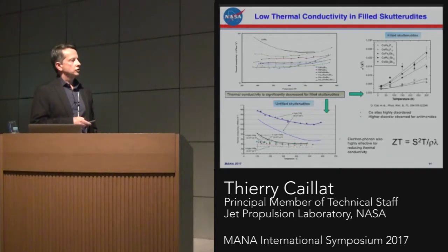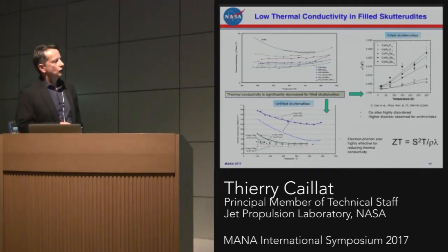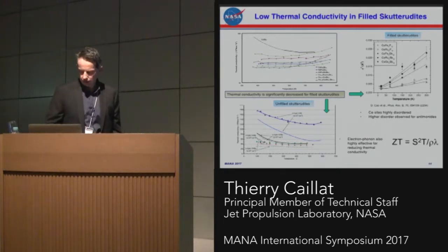One of the challenges in analyzing this decrease is that once you do this filling, you get semi-metals, so a lot of charge carriers, and you can get a lot of electron-phonon scattering at the same time. If you take unfilled skutterudites and just do straight doping, not filling, the charge carriers come from doping, not from the fillers. And if you achieve the same carrier concentration, 10 to the 21, you achieve about the same reduction in thermal conductivity. So it's still an open question whether the rattling itself is the only mechanism that yields the lower thermal conductivity, or whether charge carrier-phonon scattering also contributes. The JPL results seem to indicate that it's definitely contributing quite a bit.